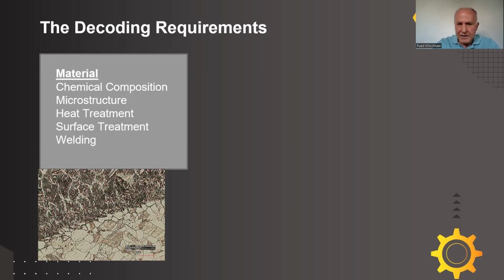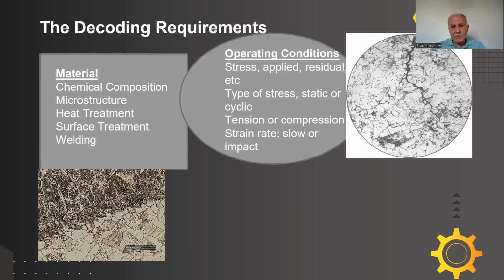So that's one about material. Another one, we need to know, as one of the colleagues mentioned, the operational conditions of that component. So it is under stress, what type of stress, is it cyclic or static, or sometimes it is a residual stress. You see, there is no stress on it, but because of some previous manufacturing processes or heat treatments, there is enough amount of residual stress inside the material. And this causes big problems if it is not being released before being installed in the component in the industry. So it is always necessary to make sure that the material that's used is free from residual stresses.